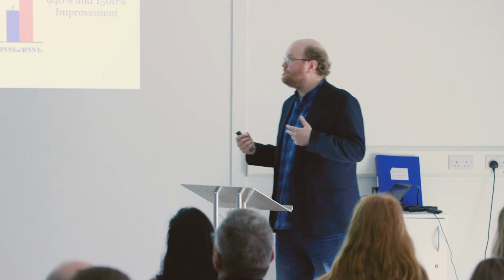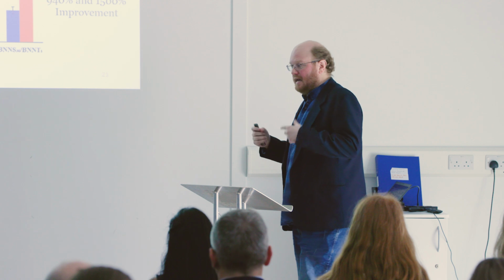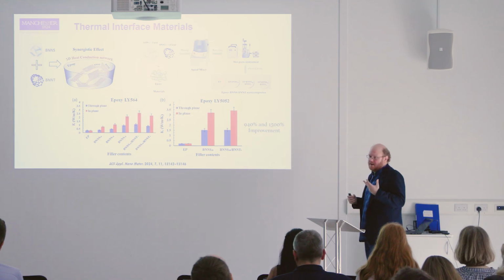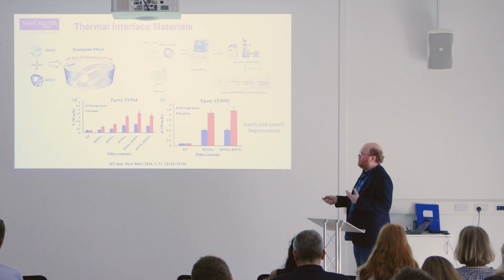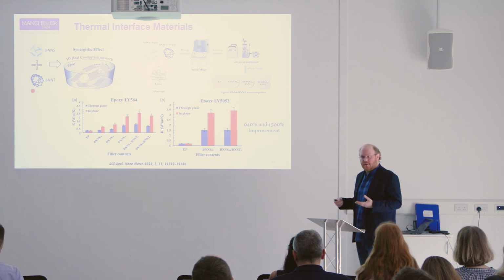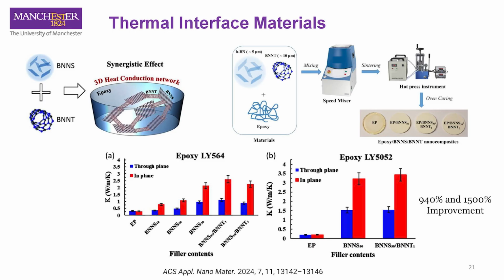One of the possible candidates that's very attractive, as I said, is boron nitride. Boron nitride is electrically insulating, so you don't need to worry about short-circuiting, but it still has very high thermal conductivity. And you can also get boron nitride nanotubes the same way that you can get carbon nanotubes. So again, looking at this synergy, instead of just boron nitride nanosheets, we can have boron nitride nanosheets and nanotubes, a 2D and a 1D material interacting together, and that gives us this synergistic interaction where we get better thermal conductivity.